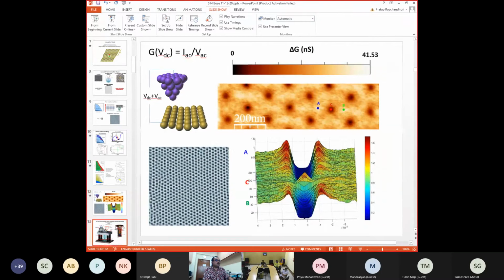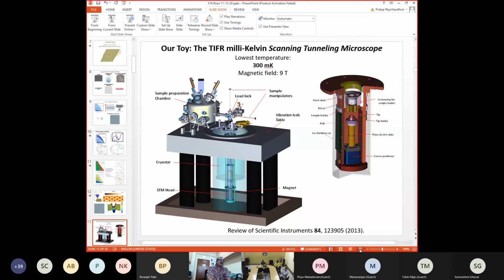Okay, so this is just an advertisement slide, and this is our toy. This is our favorite toy in the lab. It's a millikelvin scanning tunneling microscope. It works down to about 350 millikelvin, and we can apply a magnetic field up to 9 Tesla. More importantly, we have a very interesting design which allows us to do in situ measurements on thin films grown on insulating substrates, superconducting films on insulating substrate, without ever exposing the sample to air. So any STM data that I will be showing you are on pristine surfaces which have never been exposed to air, and that's very important to get reliable data.